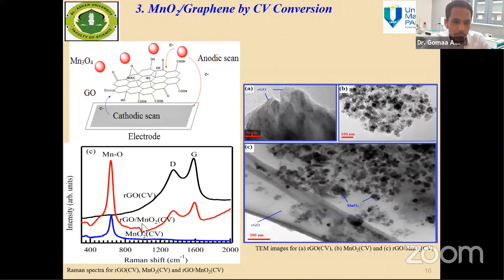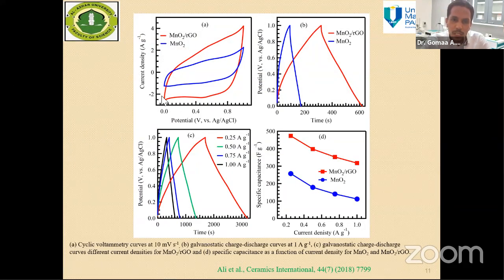So here's the Raman spectrum for pure manganese oxide and pure graphene, and the composite showing the bands for both materials, indicating the successful combination of the two materials in this composite. And as usual, we tested this nanocomposite for supercapacitor application, and it shows rectangular cyclic voltammetry and linear charge-discharge curves. And we tested for different